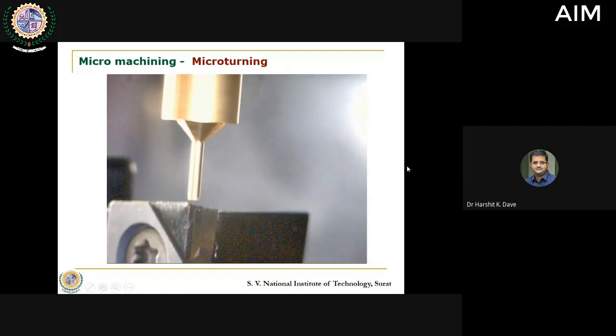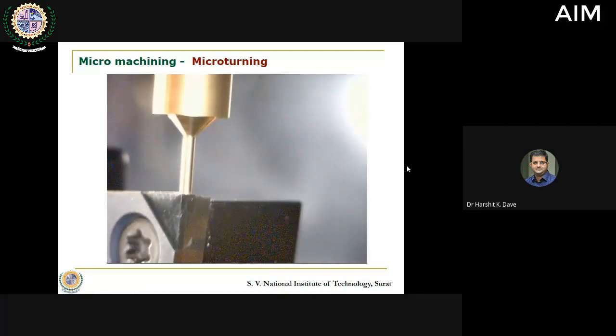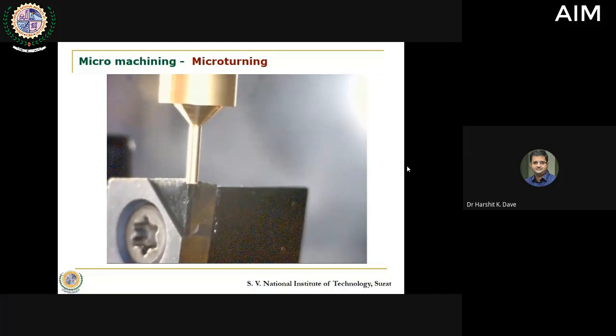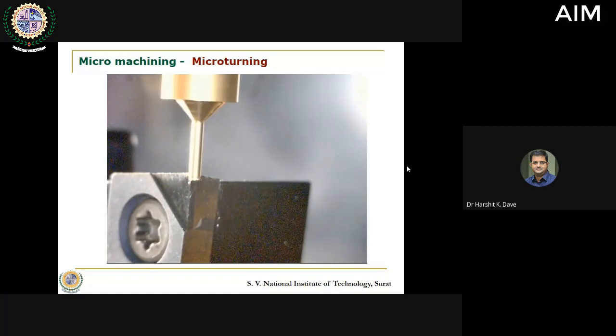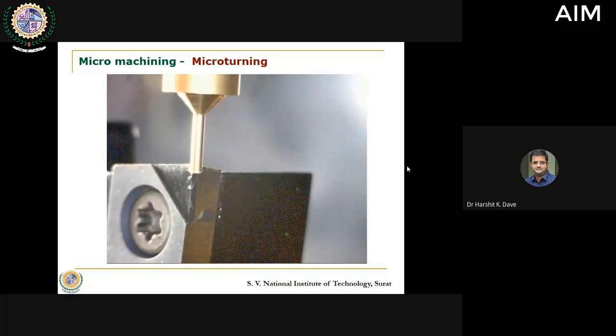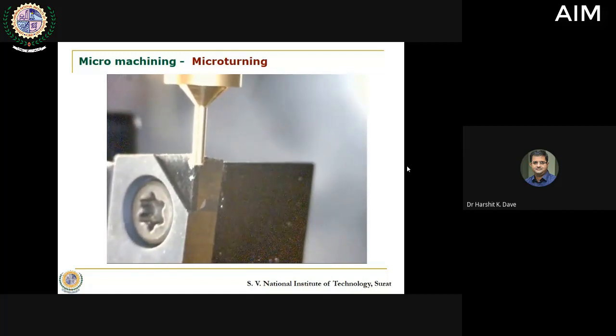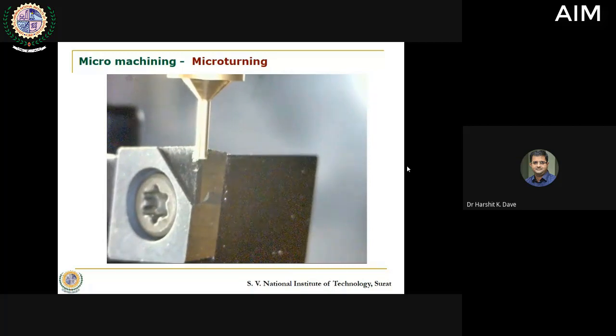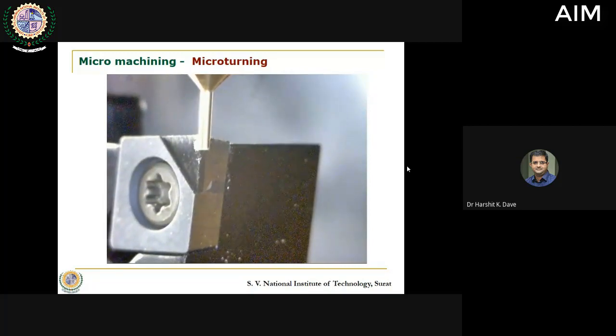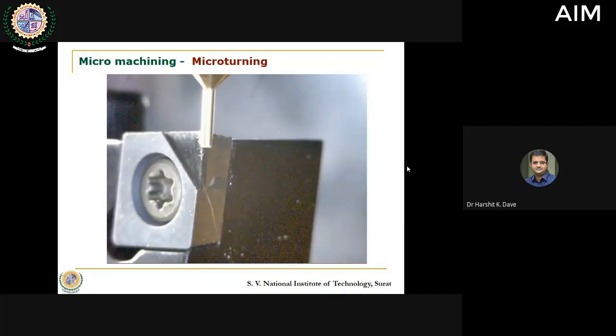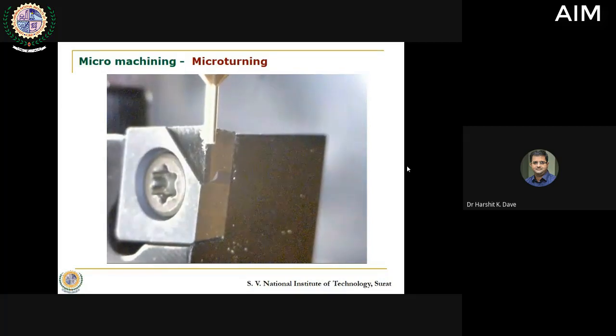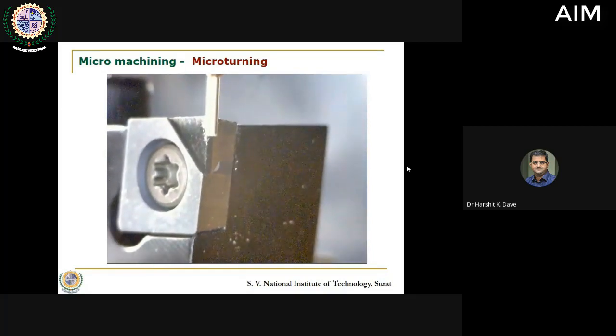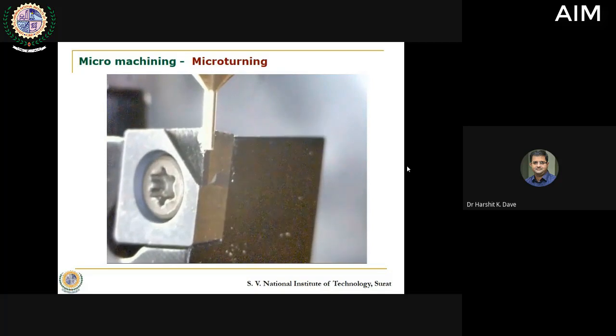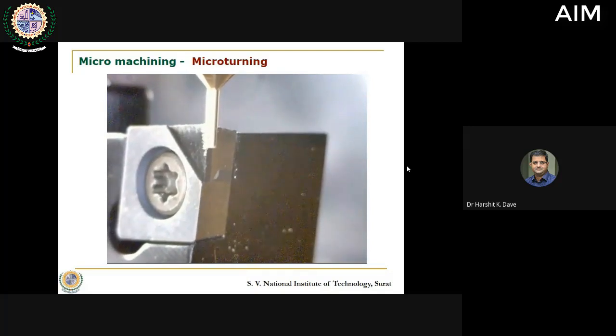This is a 1.5 mm diameter tool, and this is one of the depth of cut of 0.1 mm. You can see this is the PCD tool. The workpiece is rotating. You can see micro size chips being formed. We also studied the chips. The chip size ranges from 20 microns to around 100 microns in size.